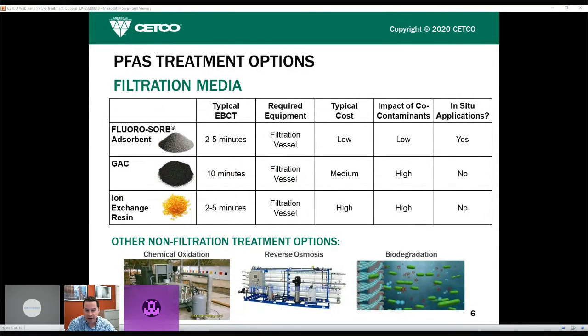So there's currently a lot of different ways folks are considering to treat PFAS. And you can look at them in filtration or sorbent types of media as ways to do that work. And what we've done is pull together a comparison of the three major sorbent medias that are used today. So FLUORO-SORB adsorbent media is similar to GAC, and it's a granular media, and it can be used in filtration vessels. And there's a little bit of difference between the two media for filtration in that FLUORO-SORB can actually be used with a lower empty bed contact time. And in fact, it's similar to ion exchange resin, somewhere between 2 and 5 minutes.